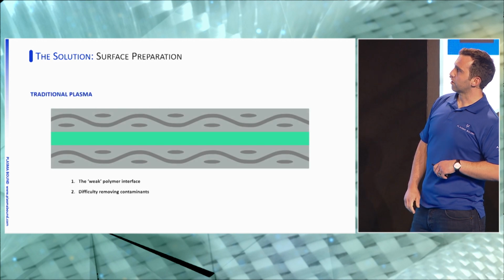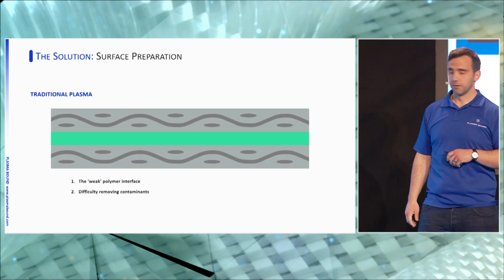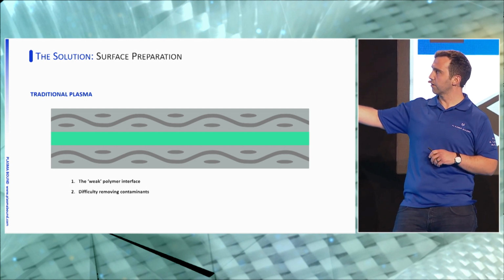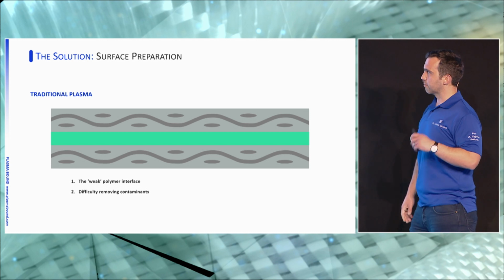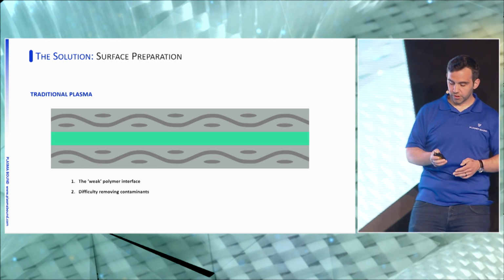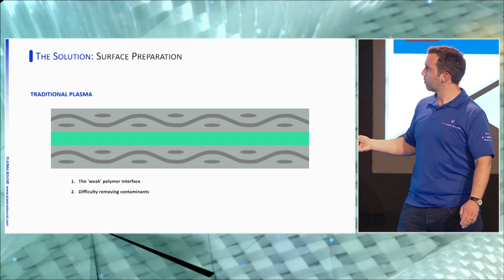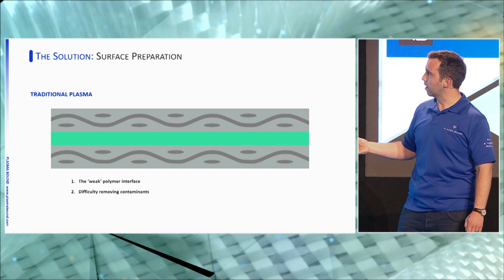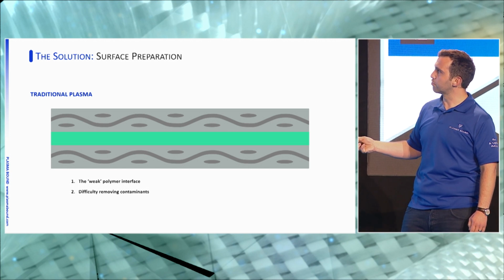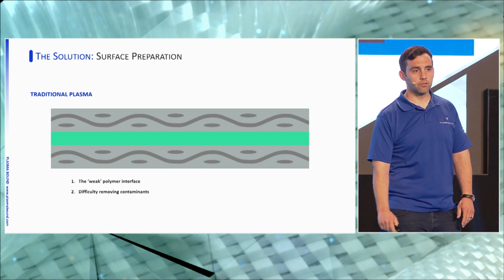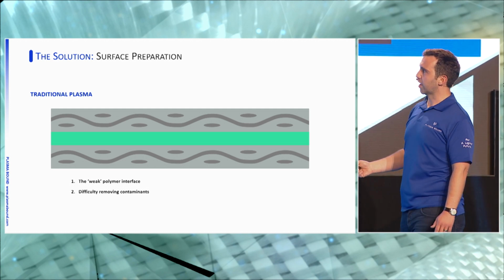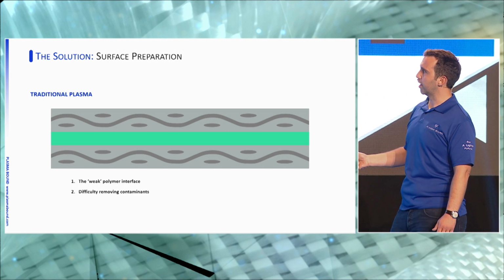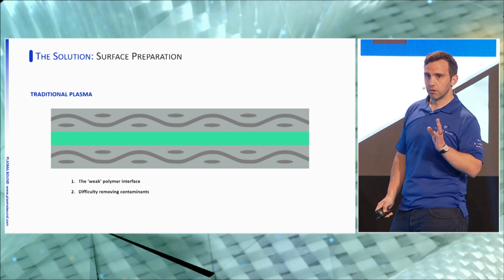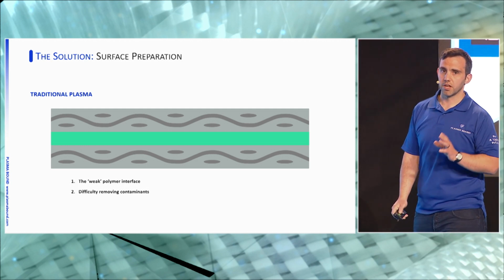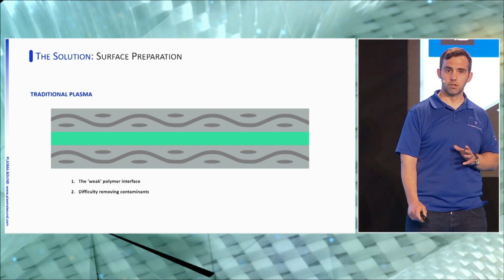So if we look at the surface that we would traditionally take, and we use traditional plasma, the weak polymeric interface here is still remnant when you do the treatment. I'll explain what that really means, but what I'm discussing here is this area between the fiber and the polymer. It's not as strong as the fiber system because it's just pure polymer. And the reason why we put fibers into composites is to reinforce them. So when you do traditional plasma, you will have the remnant of this weak polymer layer, and contaminants are difficult to remove. But if you have removed the contaminants beforehand, traditional plasma is very good at increasing the energies and causing adhesion. Now, I'll explain why I'm using the term traditional plasma in a minute.